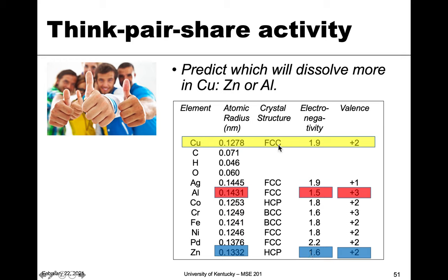Looking at crystal structure — which I glossed over — copper is FCC, aluminum is FCC, but zinc is HCP. So in this case aluminum gets that check mark. Aluminum has one criterion, but zinc has the other three. So we would say zinc dissolves more in copper than aluminum would. This was a comparative example: we compared two metals as solvents to one and saw which would dissolve more to form more of a substitutional solid solution. We didn't care about absolute values like the less-than-15% size difference — we just wanted to see which one better met the criteria.